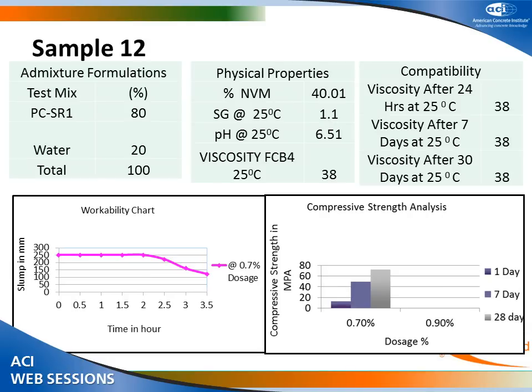64-65. Sample 12, again you can see this is a slump retention type, and this has also given almost similar slumps, and probably slightly higher than the WR1. The compressive strengths at 0.7% dosages are better than the WR type PC, which is around 66-67.